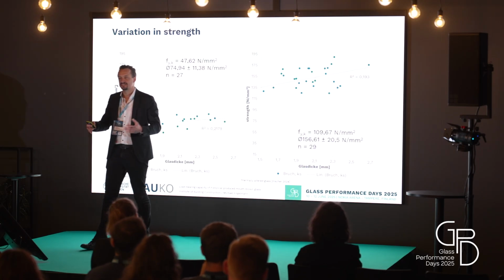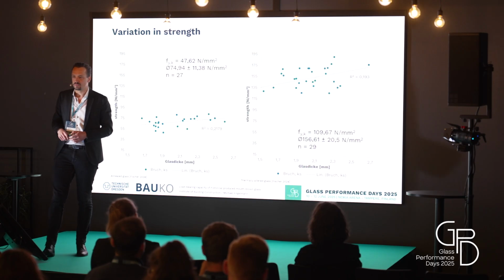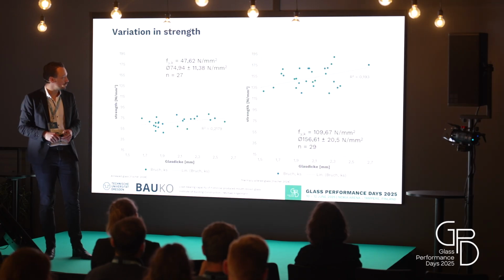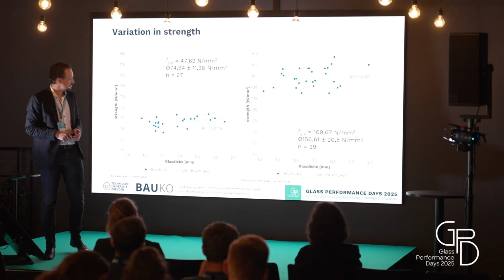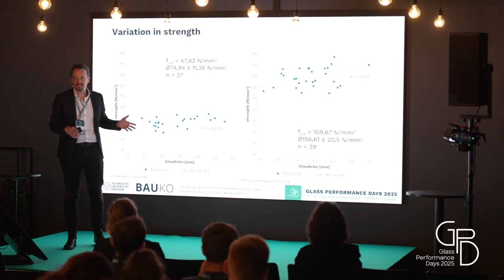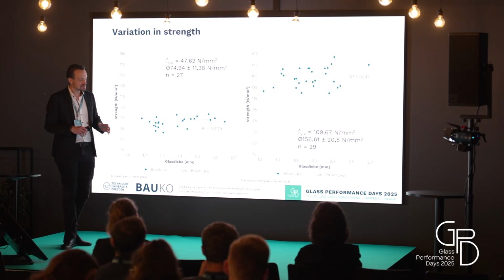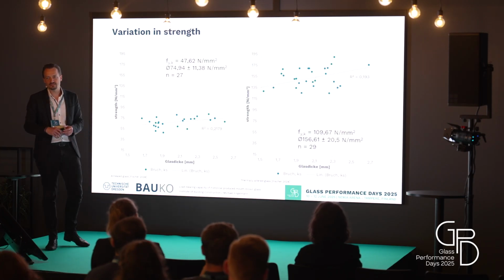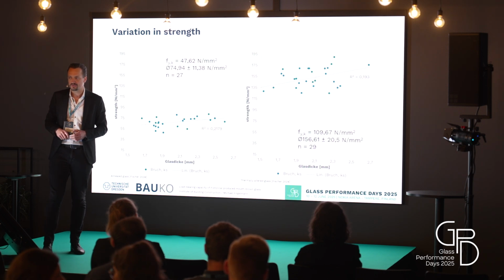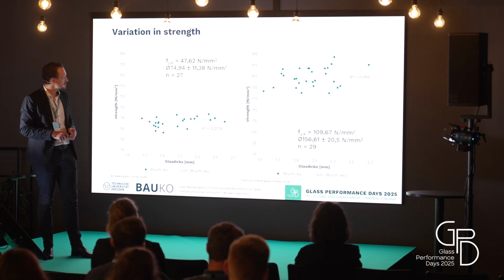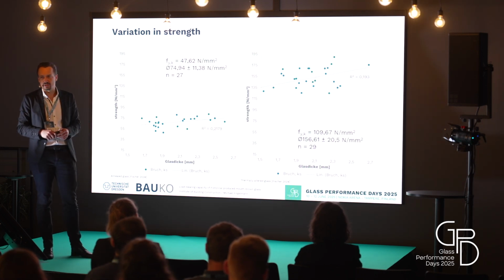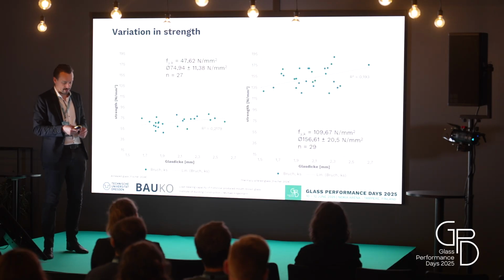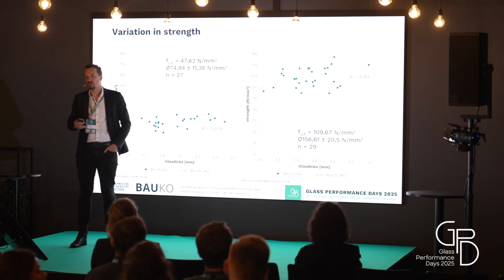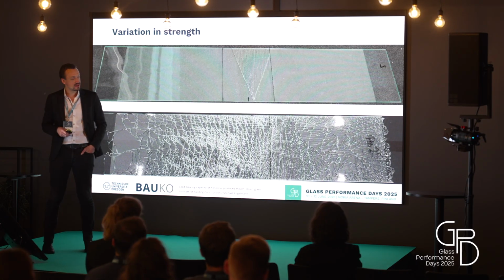So we didn't actually achieve something we would like to see for fully tempered float glass. But this just gives us an indication that we can almost use this mouth-blown glass in a comparative way as we would use annealed float glass, but we do not achieve the actual strength values of fully tempered glass. And of course, when we talk about those two glass types, we also have to look into the breakage pattern.